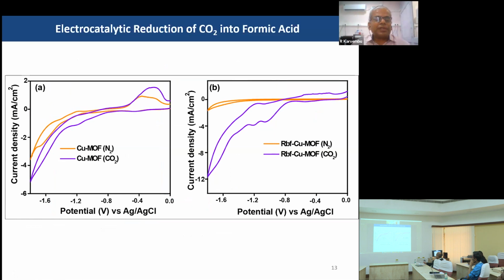We used cyclic voltammetry and linear sweep voltammetric techniques to understand the electrocatalytic property of the pristine copper MOF and riboflavin-modified copper MOF. Using copper MOF as catalyst in the presence of nitrogen-saturated 0.5 molar sodium bicarbonate electrolyte, you could see a very slight increase in the current density. But when we used carbon dioxide-saturated electrolyte, a prominent increase in the current density was observed.